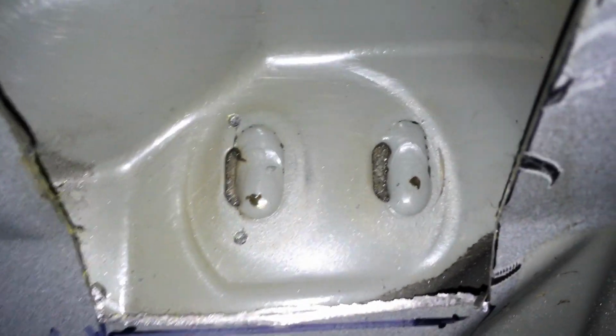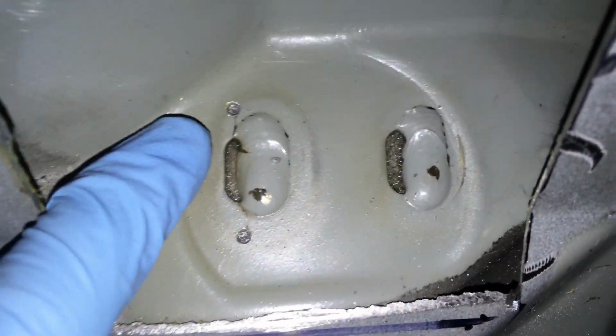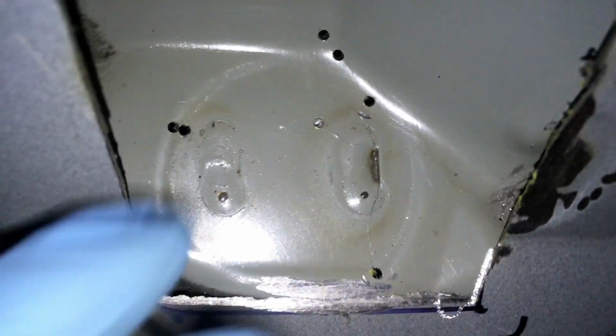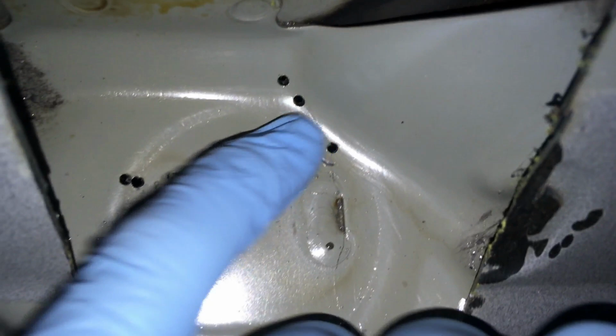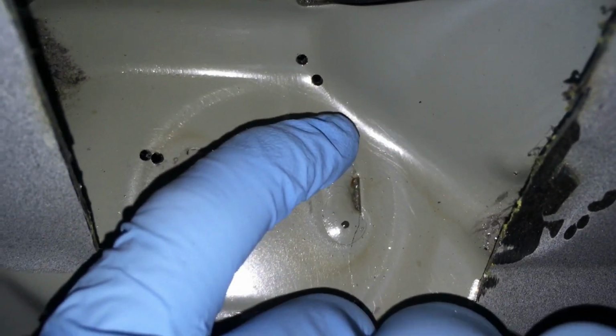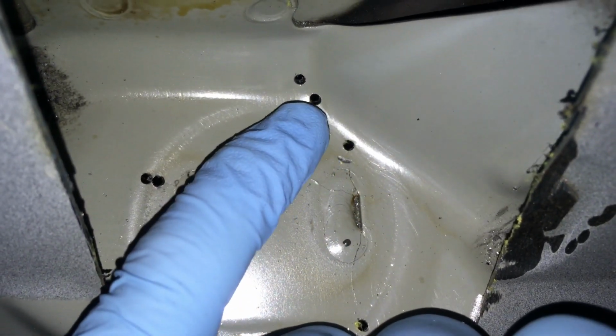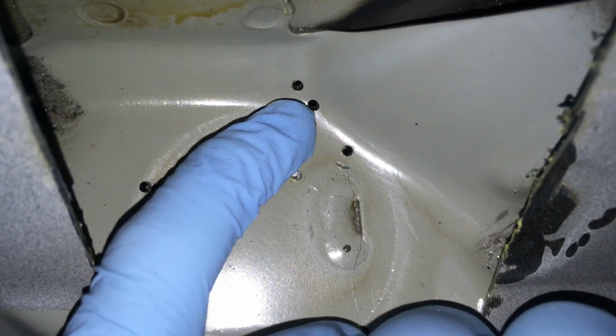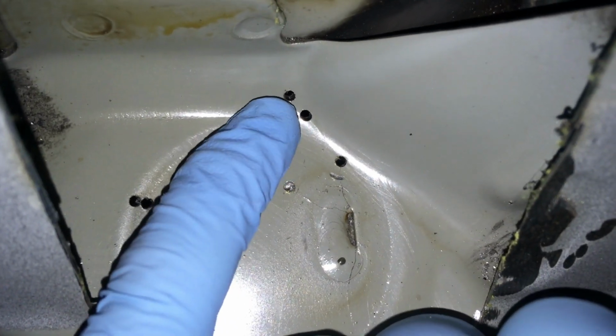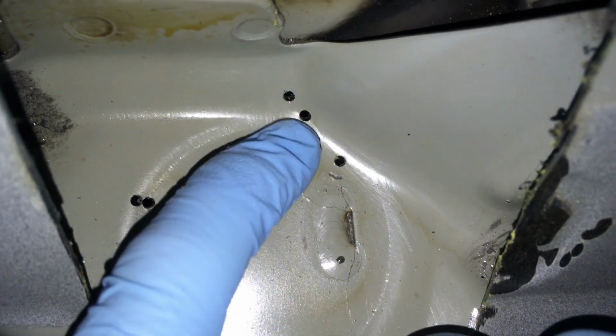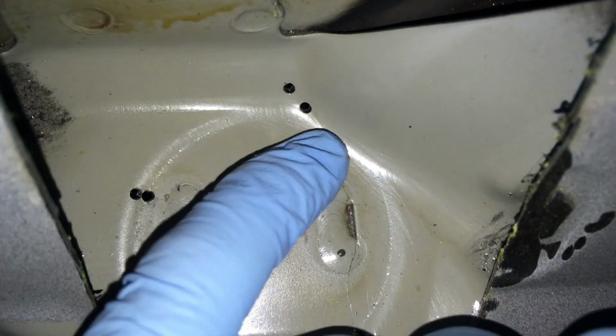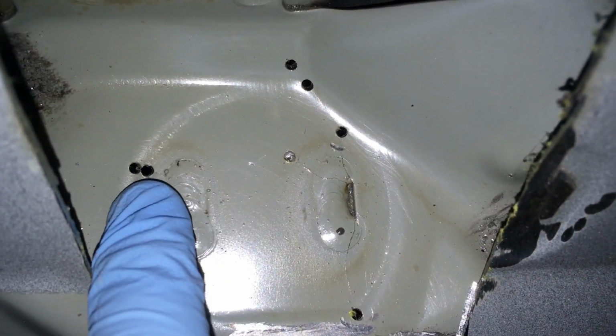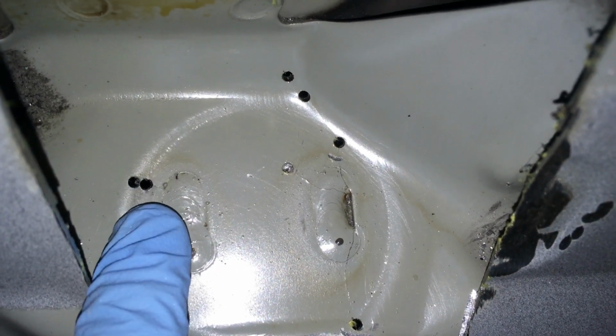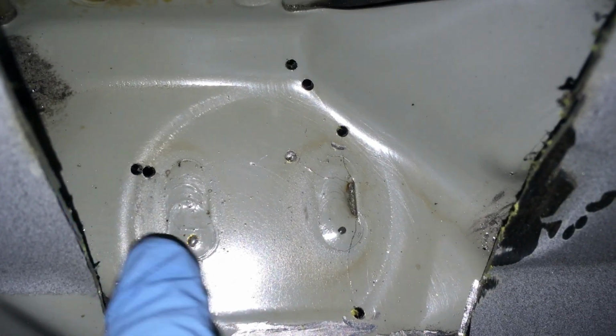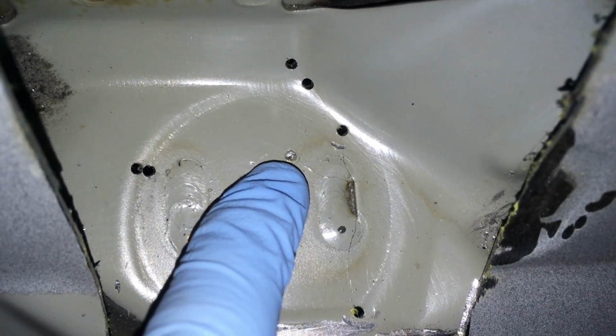I've stop drilled the ends of the cracks so you can see them a little bit clearer now. Two on this MIG weld here, and then quite a few on this MIG weld. This one kept this cracked. You could see a slight reflection in the light where I was unsure if it definitely was a complete crack or just a slight marking in the metal grain. But I'm pretty sure it chased it all the way up here, so there's two more extra cracks on that, two more extra stop drills on that crack there. And this one, as soon as I centre punched it, it grew even more when you shock the metal, so I had to have a second drill, and there's one here just ending about in the middle now.